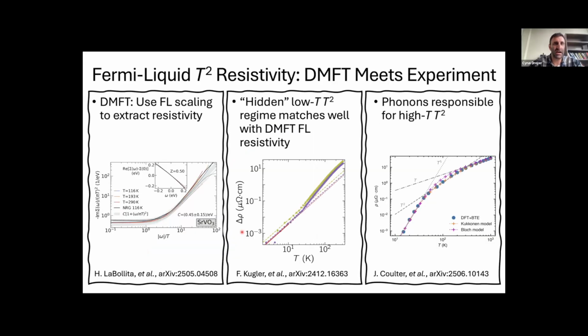Okay, so I think I'm just about out of time. So I hope I showed you some tricks that we use to extract converged Fermi-Liquid resistivities in high conductivity, low scattering rate materials from DMFT using the Fermi-Liquid scaling. And that in these materials, and I think many others, there is a hidden low temperature T-squared regime that actually matches quite well to our DMFT Fermi-Liquid calculations, and a higher temperature T-squared regime, which we attribute to electron-phonon scattering in a cylindrical Fermi surface. So thanks for your attention. I'm happy to take questions.